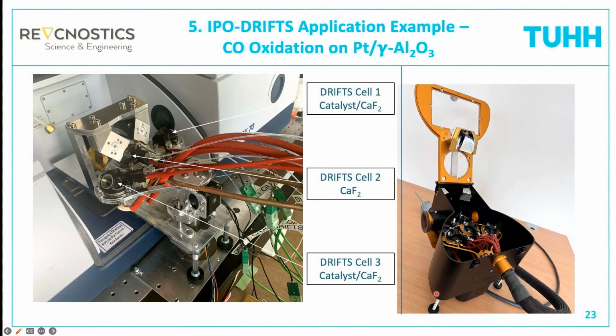Okay, so now back to the isopotential operando experiment. If we want to do this properly, we need more than one DRIFTS cell that we can use to perform ideally these 4 measurements at one reactor position before we move to the next position. But if you try to put 4 cells under such optics here for the IR spectrometer, this is difficult. We ended up in this design here with 3 chambers, and in the newest version we have only 2 chambers.